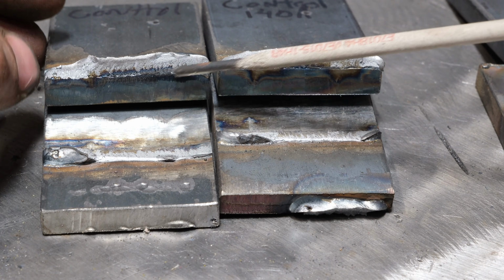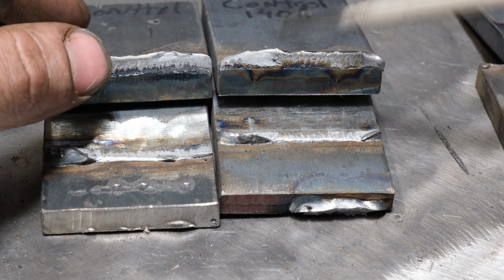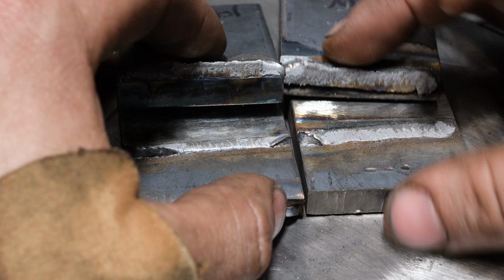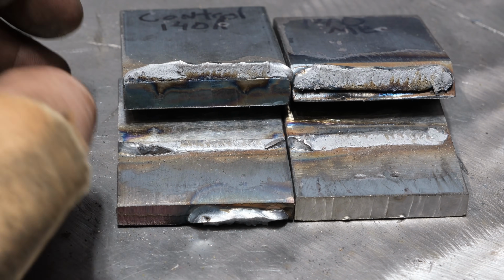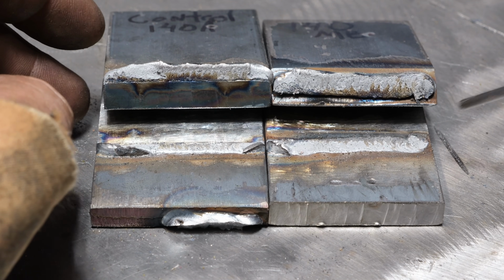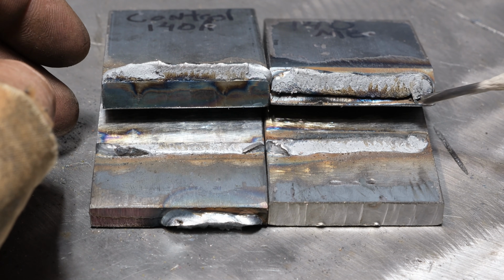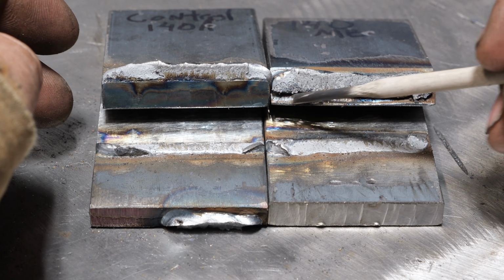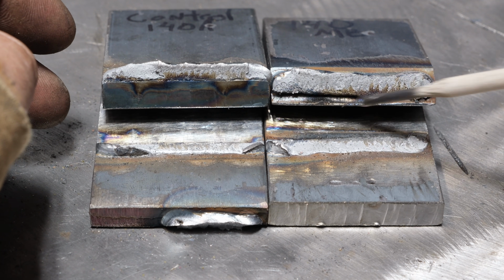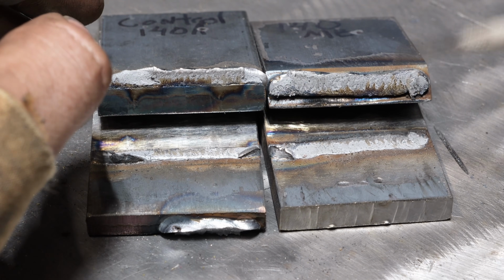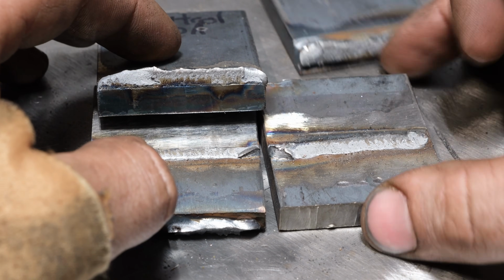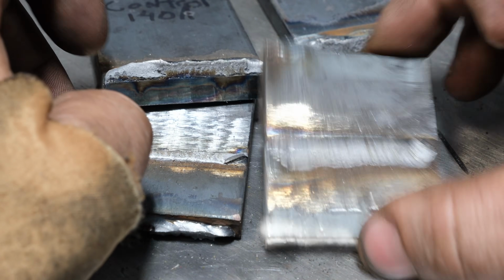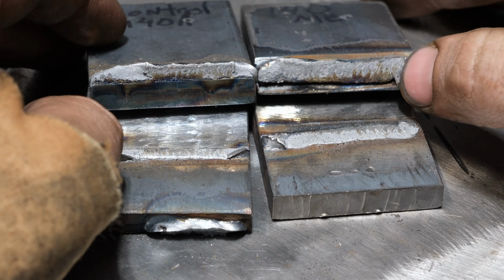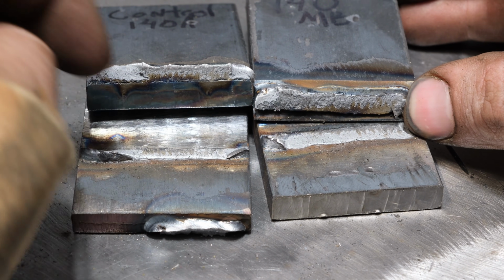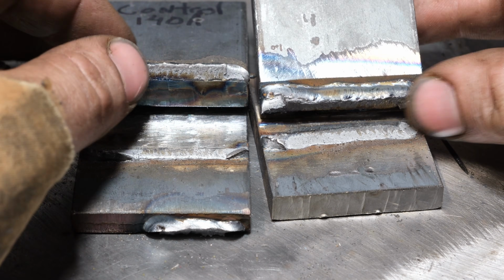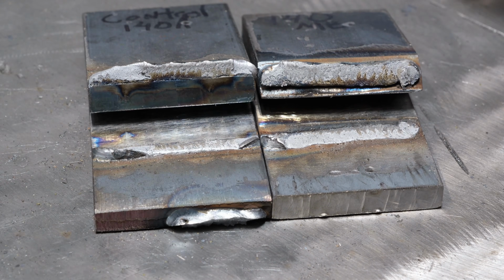I mean, there's none whatsoever, and there's a little bit here. A little bit will go a long way on this. Now, when you compare to the beveled plate, which obviously did increase slightly in strength, this guy, even worse breakdown of the edge. You got what essentially is internal cold roll here. I mean, there's a cavern so dark under there you could hide bats or gold bullion in there. And interestingly enough, we do have a wider area of fusion there, but that could be just due to travel speed. There's more metal deposited here than on here, so I likely went a little bit slower. Again, all variables that are difficult to control.